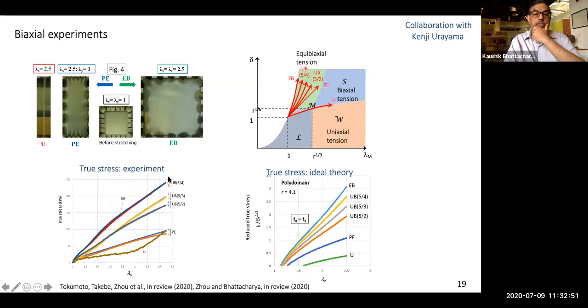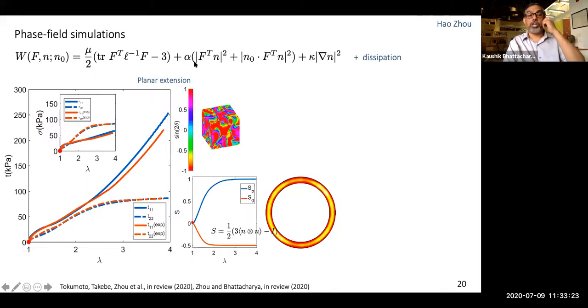So these are the experiments, and you see that here you have the stresses in two directions, both the x and the y, and you see that the stresses always agree, as we had predicted according to the theory. So this very simple theory, which you can compute explicitly, describes this behavior. Of course, you don't describe the lower part of this behavior because you have made some approximations to obtain this theory.